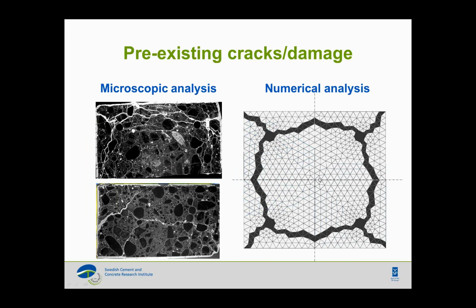Then we tried to check the crack pattern we got from the simulations in comparison to what we have in the piles through microscopy analysis. What you see is that in the microscopy analysis we saw cracking in this direction, all the way from this reinforcement to this and then down here. And that's what we also see: due to expansion from sulphate attack, we have cracking all the way to the reinforcement, to the corner, and all the way to the other side of the cross section.